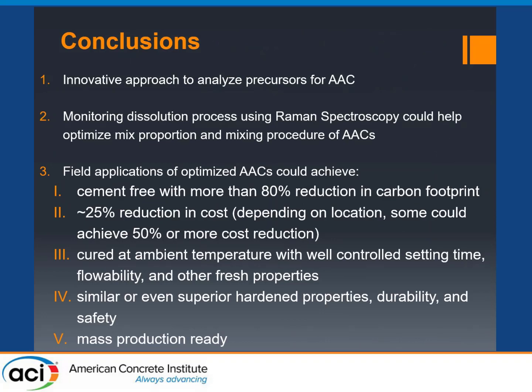So in conclusion, we have some better ways to analyze precursors. We also monitor the dissolution process using Raman. So that could help us optimize the mix proportion and mixing procedure. Some field application of AAC could achieve cement-free, more than 80% reduction in carbon footprint, more than 25% reduction in cost. That is depending on location. In some cases, we could achieve more than 50% or even higher reduction in cost.